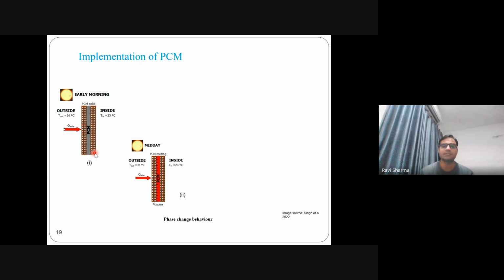Now what happens as the day progresses, we reach the midday around 12 p.m. or 1 p.m. The outside temperature increases from 26 to 35. But as the temperature increases, the heat starts transmitting through the wall. So what you can see is the PCM was of gray color. Now the PCM is of red color. So this gray color shows the solid portion. The red shows the liquid portion. The PCM is able to absorb this entire energy and then starts getting melted. So when the PCM absorbs energy, that means they are preventing this heat from getting inside the room. They are able to absorb the heat. So when the heat doesn't go inside the room, the inside temperature still remains the same. As you can see, 23, 23. But the outside temperature increases. That means in the morning time we feel comfortable. In the noon or afternoon time we feel comfortable.